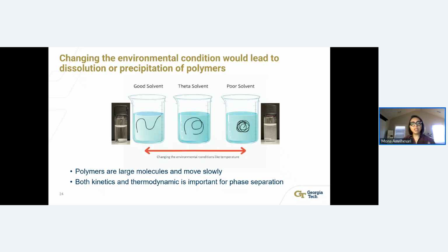But changes in environmental conditions, like temperature, can change the quality of the solvent from good to bad, or from the theta solvent, when all the attractive and repulsive forces are in equilibrium with each other. So the polymer is in its most relaxed form, and changing from theta condition to good and then to poor, the phase separation is happening. And the polymers start going from the coil to the globule state.